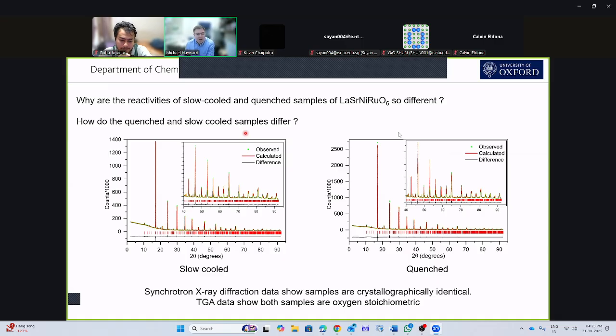The Diamond Light Source is about 20 miles away from Oxford, so we can make regular use of the synchrotron X-ray beams there. And if we take diffraction patterns of the slow cooled and quenched samples and fit them to models, we find that they're identical. Their lattice parameters are identical to about 4 decimal places. The atomic positions are identical. We can chemically analyze them and show they've got the same amount of oxygen.